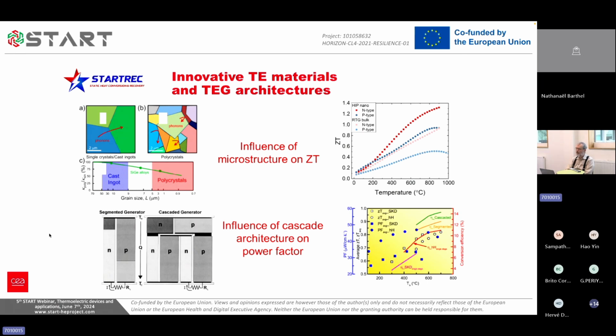You see here conventional microstructure A, and if you have a smaller microstructure, then phonons will disperse more easily, and you get lower thermal conduction. And you can see that on the graph, where using the HIP, that's high pressure. Bruno, remind me what HIP means. Hot isostatic pressure. So this is a means for obtaining this small microstructure, and you see how the ZT increases by just reducing the particle size, the grain size in the material. So that's one thing that we are going to investigate in STARTREC.